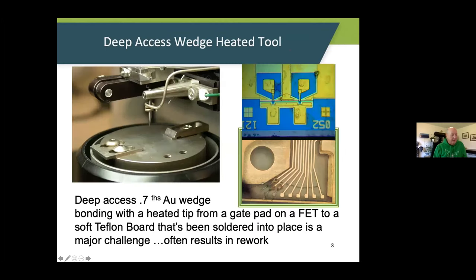And this right here is probably the most challenging wire bond application out there, if you ask me. That is a deep access 7/10 gold wedge with a heated tip. And you're going to go to a gate pad. This is a dual FET. Some of these gate pads are only 2 by 2 mils, so that's like 50 by 50 microns. So you really get one shot at it.